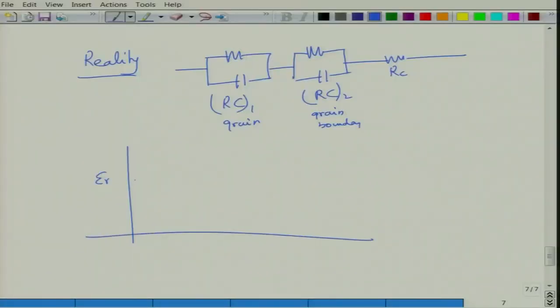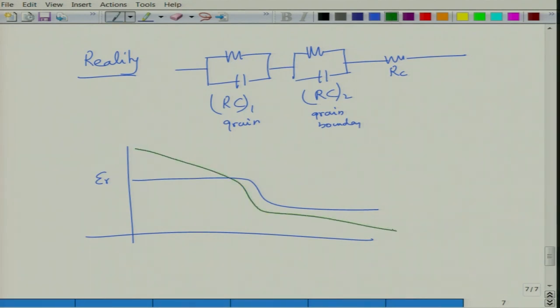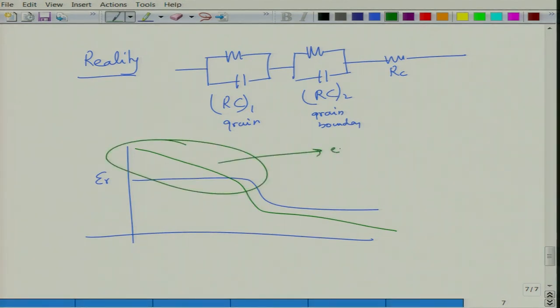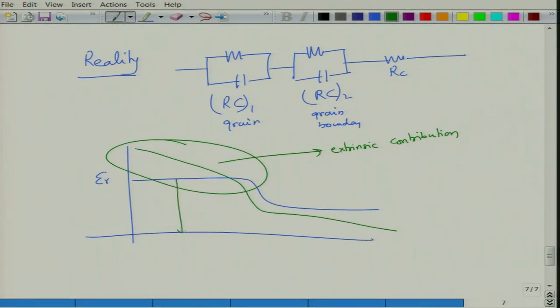You need to separate the resistive contribution from the capacitive contribution. For example, when you see dielectric constant variation as a function of frequency, ideally it should be flat, but in most cases you obtain a decrease with frequency, suggesting extrinsic contributions such as defects and vacancies. From just this plot it is difficult to tell the true dielectric constant, which is why you need to carry out impedance analysis.